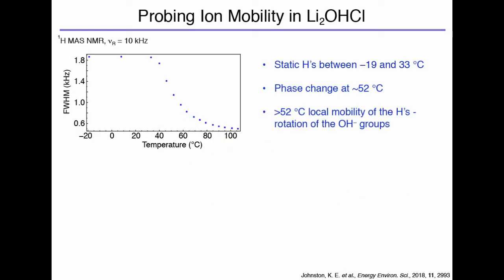So what we can then do is measure how much that line is changing as a function of temperature by looking at something known as the full width at half maximum. And if we do this, we find that between minus 19 and 33 degrees C, there's basically no change in the line, which in terms of NMR tells us that the proton is totally static at that point. It's not doing anything. After that point, it does start to move. And it looks like you can observe the phase transition, which is what we expected, but it also looks like there's some form of mobility of those OH groups, probably something like a rotation around a point.